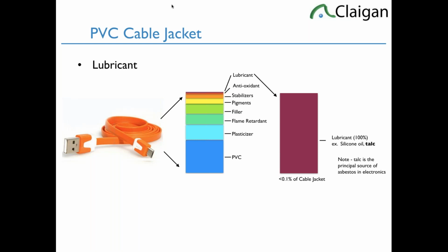One of the problems with industrial talc is it's normally co-mined with asbestos. And so very commonly, maybe 1 in 3, maybe a little less now, when we find talc in a power cable, we find asbestos, which is a Canadian or Australian non-compliance, where we have the asbestos contamination in the talc. And it's one of the many reasons why baby powders are now cornstarch instead of the original talc, because talc has most of the properties that asbestos has, and has some of the same negative effects, and often can have asbestos right in it.